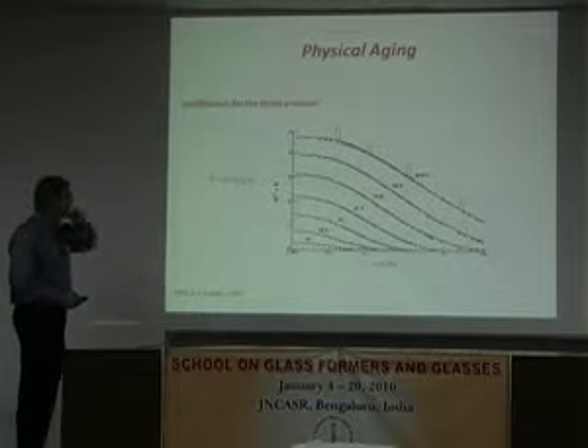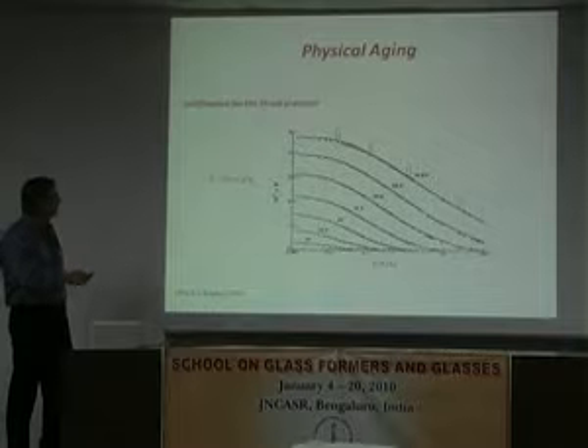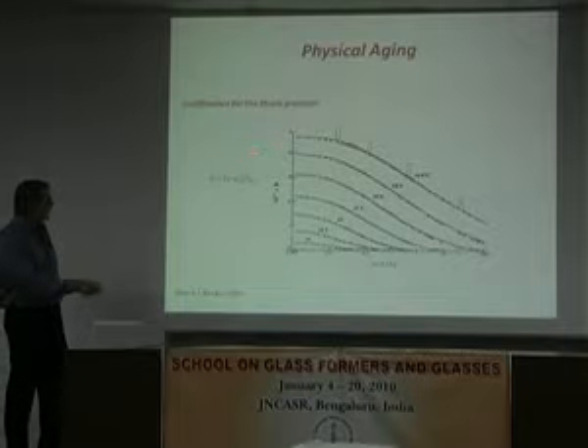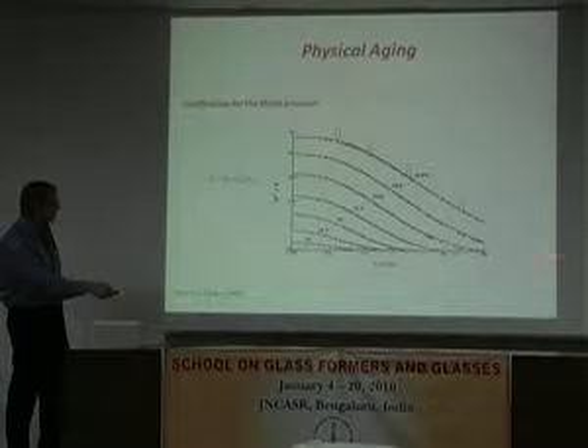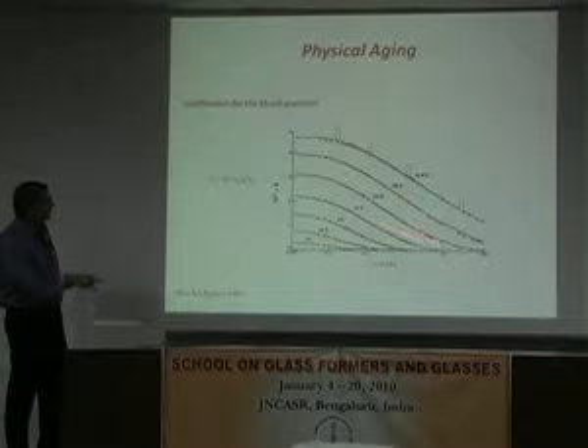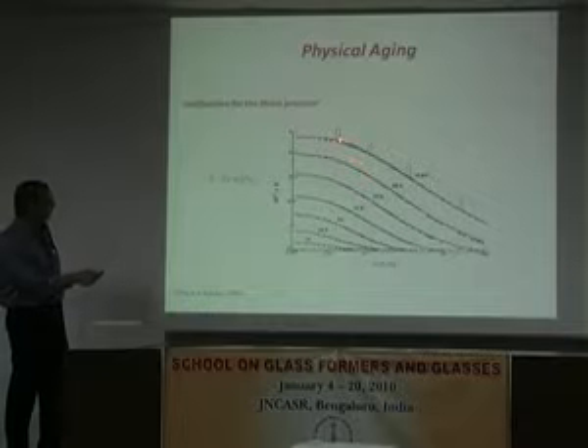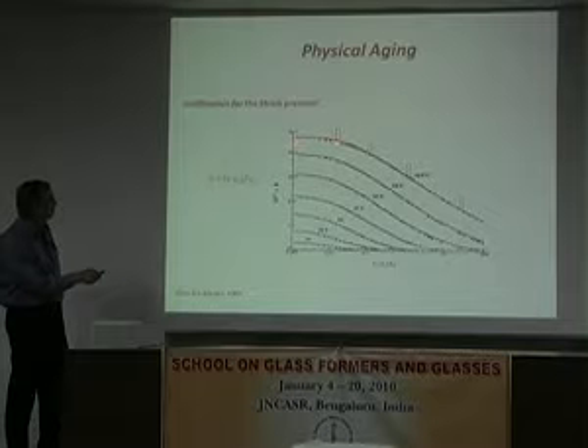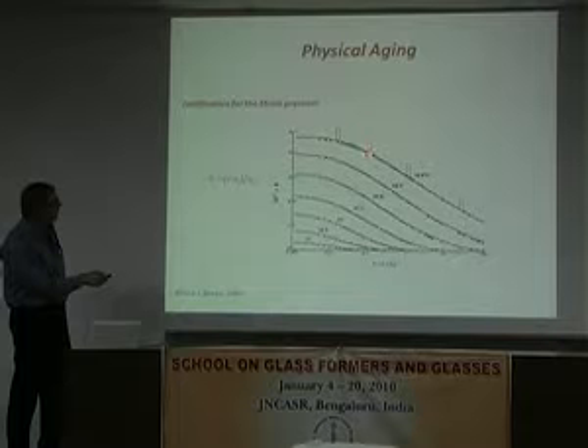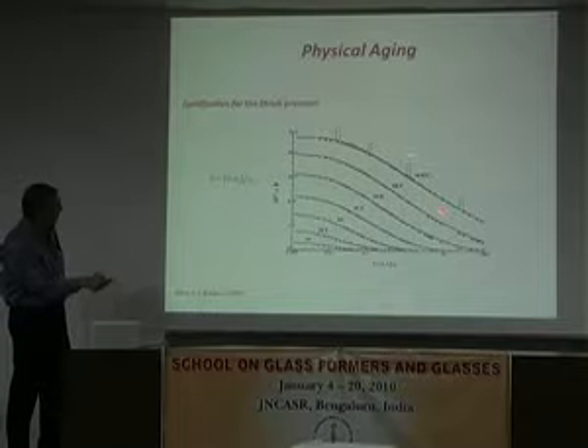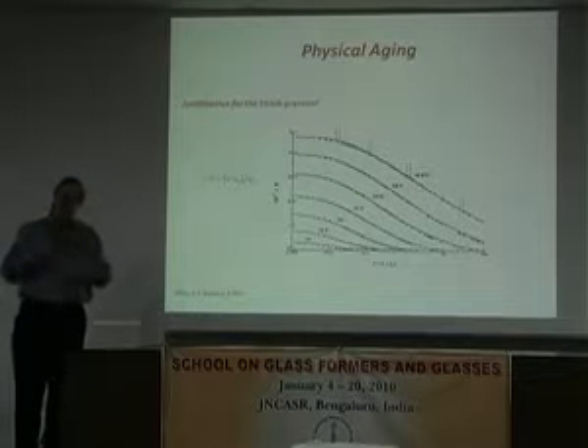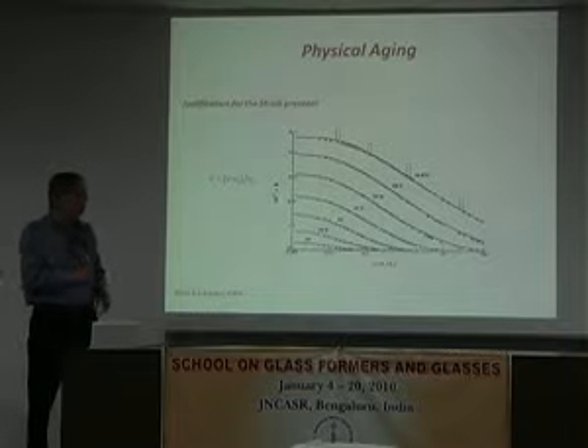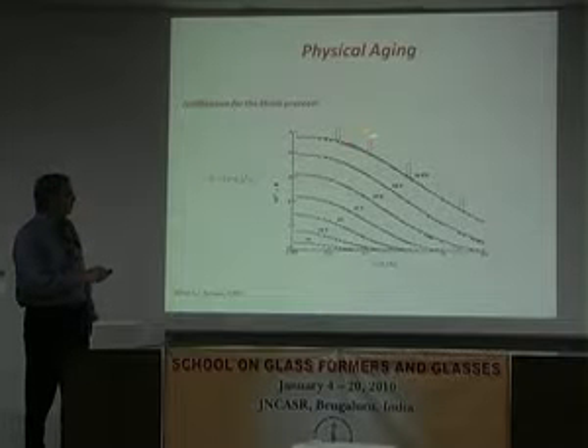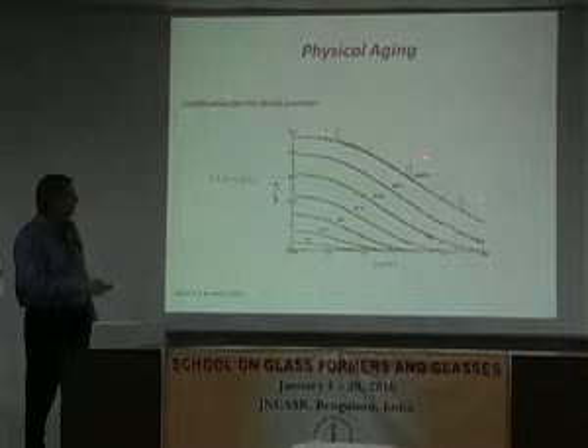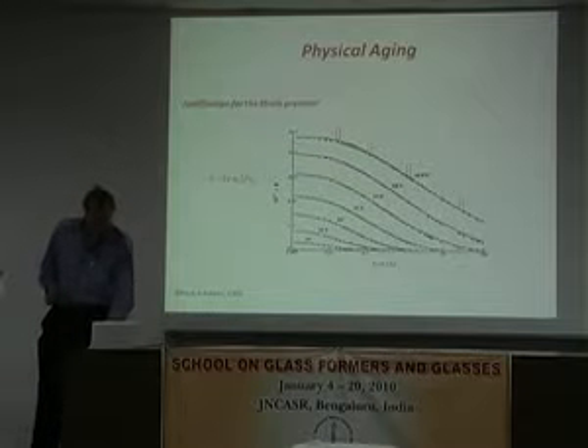And here's the justification for Struik's protocol. This is the volume departure from equilibrium versus log time. And you recall I showed this structural recovery behavior. And Struik said, I want to take a snapshot, basically. So this time has to be short relative to this time, and you don't want this changing structure affecting what you're trying to take a picture of. Okay, so that's the general idea. And these are equally spaced. You can see they always take up about 10% of the logarithmic time.